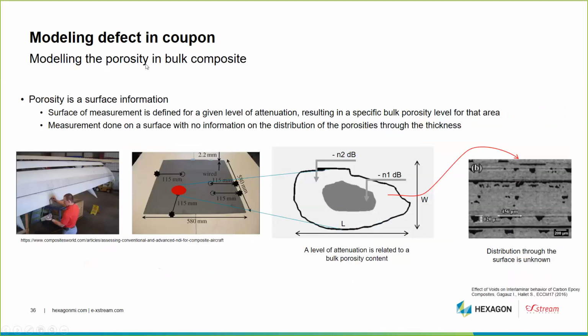The third defect that we can deal with is the porosity. When we had to think about the way we want to define the porosity, we need to understand that the porosity is surface information. What is done typically in production is that a technician has an ultrasound system and tries to detect the porosity through an attenuation of the signal. When a different attenuation is identified over the surface, it means that we suspect the presence of porosity through the thickness.